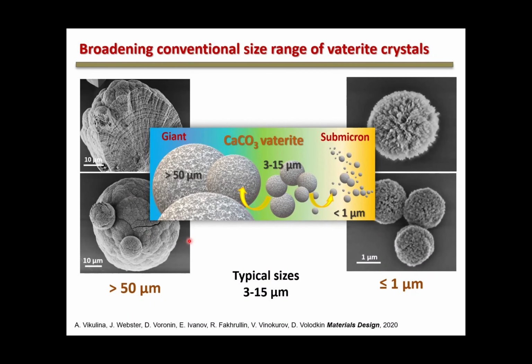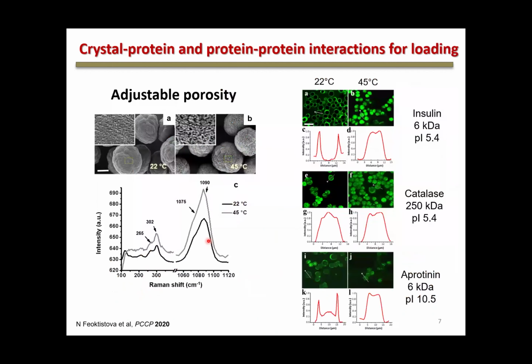And in all these cases, we don't use any additives, which is very good for multiple applications where it is hard to get rid of additives or any other additional components in the system. So as I mentioned already, they are porous, and porosity can be controlled as well. If you prepare the particles at different temperature, which is still not that much different from ambient temperature, you can get control over the porosity of the particles, which we have tested with different biomolecules, in this case, fluorescently labeled protein as probes.